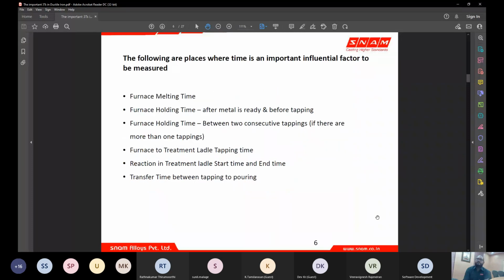So I have listed down, from the furnace till the last pouring, where all the time is going to be measured, and how important it is. So the furnace melting time: the time taken from the solid charge till the liquid metal is generally measured as furnace melting time. This has a direct relationship with the amount of metal to be melted and the frequency or power input you use for melting. And again, it depends on the charge material you use.